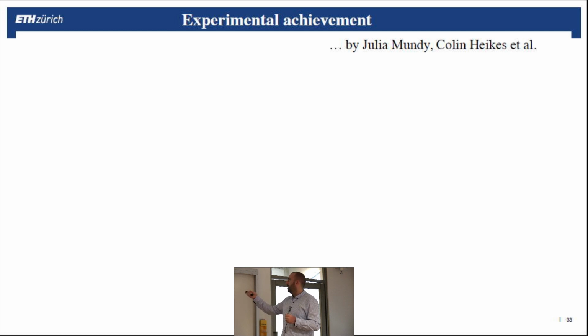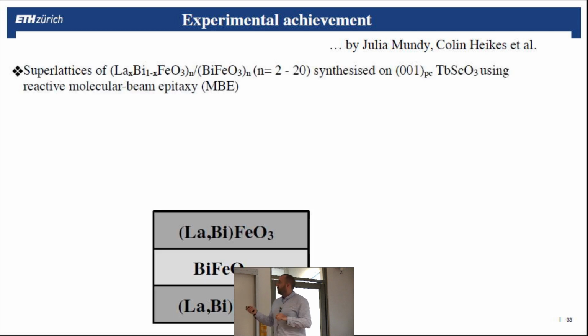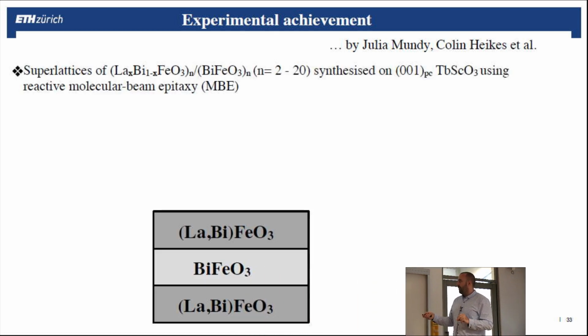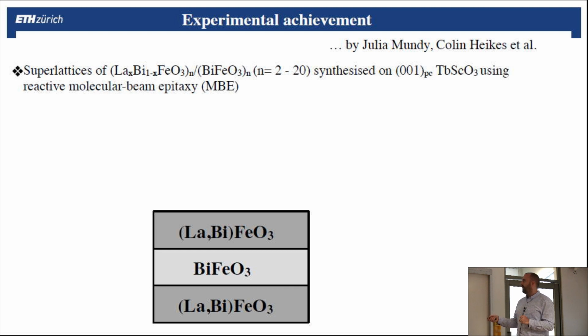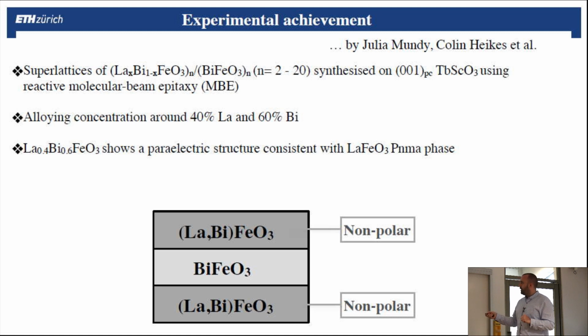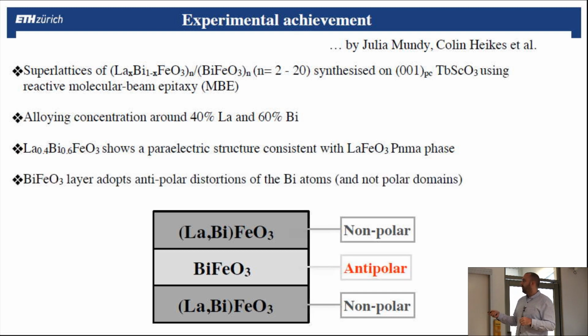And that was actually experimentally achieved by Julia Mundy and her collaborators, where they considered superlattices of bismuth ferrite surrounded by lanthanum bismuth ferrite, meaning that they replace a percentage of the bismuth by lanthanum, and they did that for a concentration of around 40% of lanthanum and 60% of bismuth. And by doing that, for this concentration, this material is not polar, and this one in the ground state is antipolar. So you would expect that this could go to a non-polar phase. And that's actually what happens.